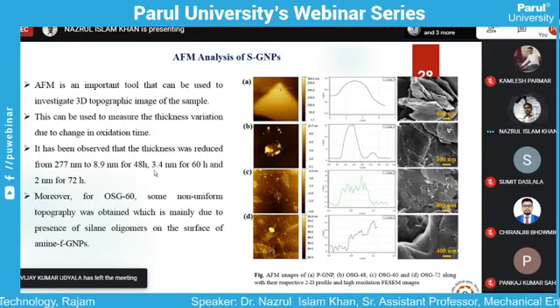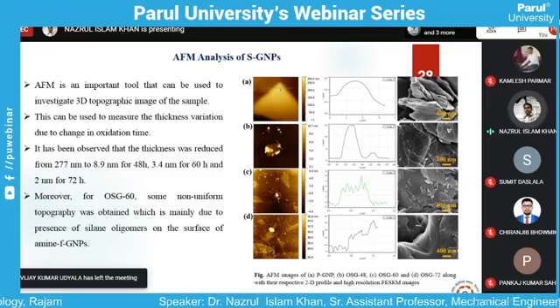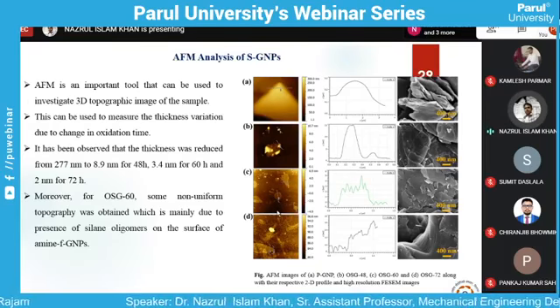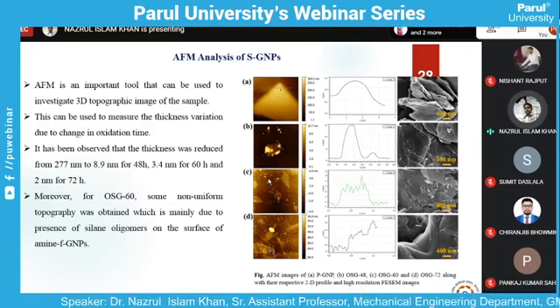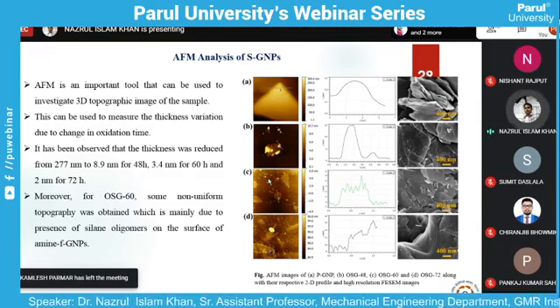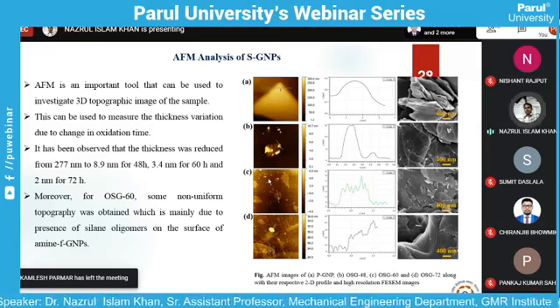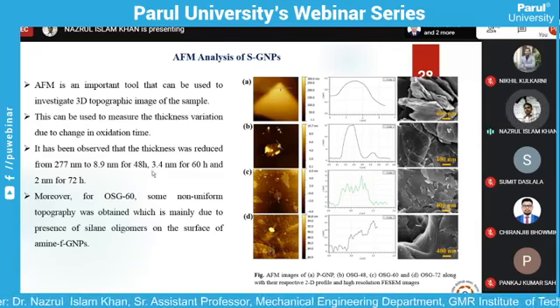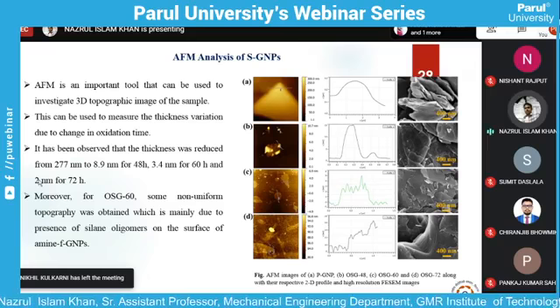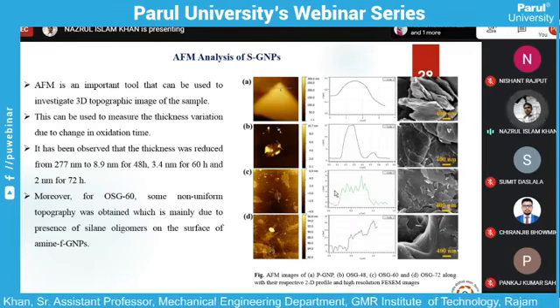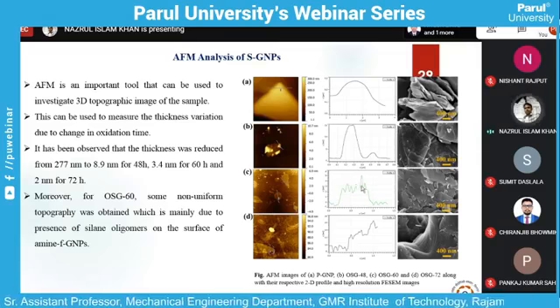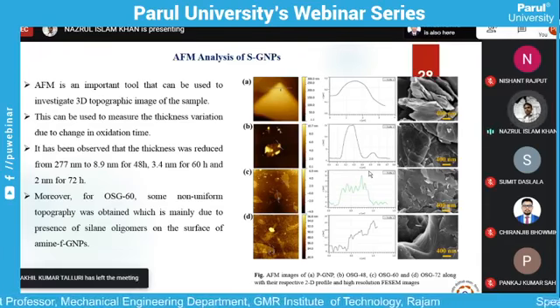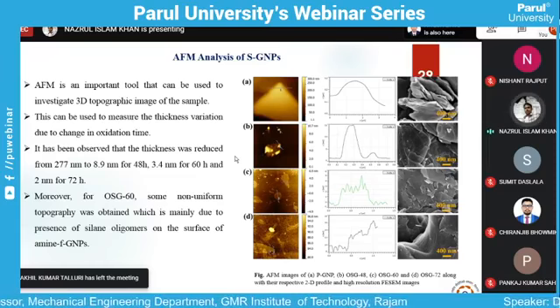So again, we did atomic force microscopy. We measured the thickness of this graphene sheet, and we found that with increase in oxidation time - we varied the oxidation time as 12, 48, 60, 72 hours like that - we increased the oxidation time, and at 60 hours, we got near about 2 nanometer thickness of graphene sheet. But on scanning range, you can see this kind of zigzag nature. Why? Because during exfoliation, we are also adding functional groups on the surface.